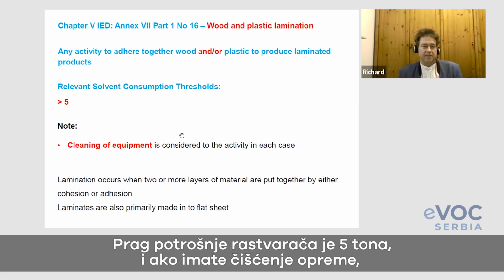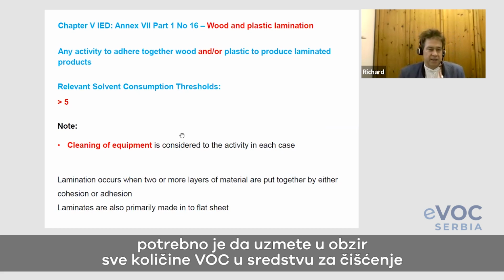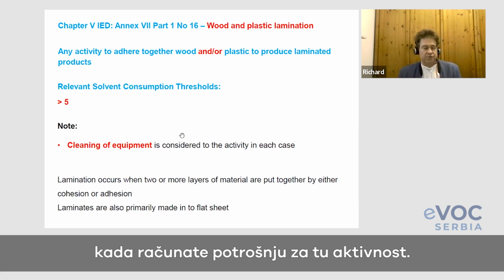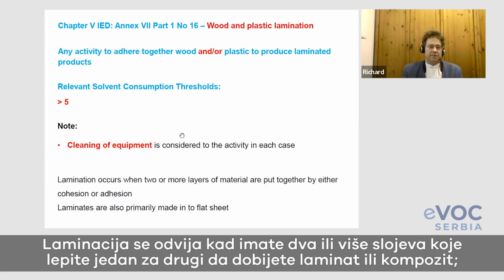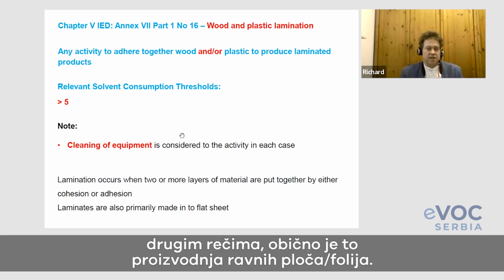And please keep in mind, if you have cleaning of the equipment, all the VOC content of the cleaner you must take into account for that activity. So that lamination takes place when you have 2 or more layers and you glue them together to have a laminate or composite. In other words, normally it is the production of flat sheets.